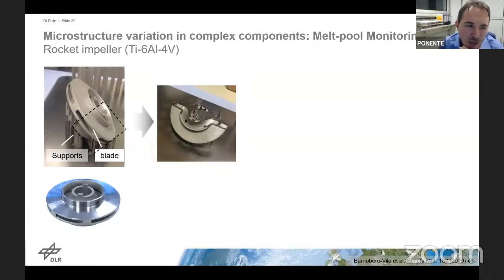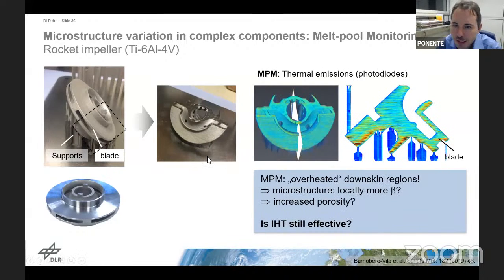And we did that by producing one of those impellers with this very high energy SLM parameter set that gives these nice alpha beta stabilized microstructures here. We only manufactured part of that impeller, a cut from that impeller to a certain height. And at the same time, we recorded this melt pool monitoring data shown here. And on the right-hand side, you see a cross section through this 3-dimensional data.